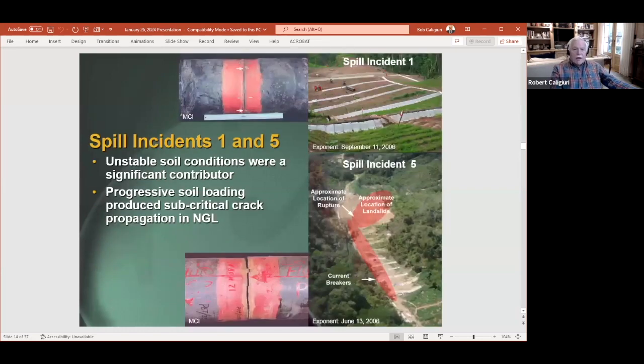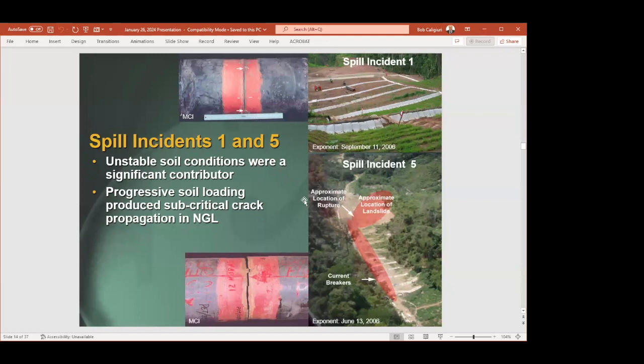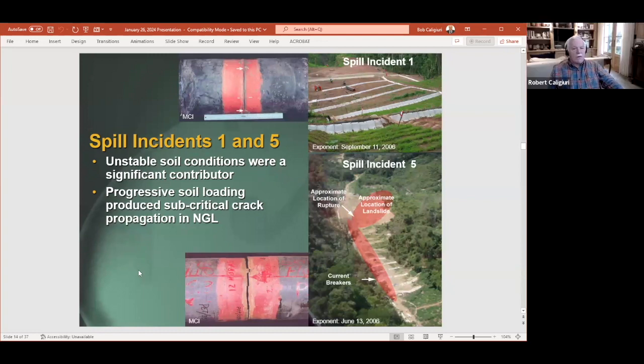Let's talk a little bit about what happened. Spill incidents 1 and 5, both of which occurred in the Amazon area. These unstable soil conditions, mudslides, and moving soil was a significant contributor. And basically, as the soil moved, it put increased loading on the pipeline, produced subcritical crack propagation in the natural gas pipeline, which ultimately led to the failure that you see in the picture down below.